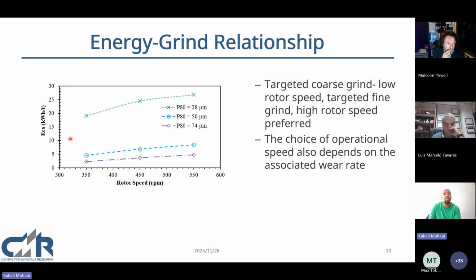As you can see, the specific energy consumption increases with increasing rotor speed, but the curve shows a decreasing trend, so the gradient decreases as the rotor speed increases. However, as much as this data could show that operating at high speeds in stirred milling would be beneficial, there's also a potential impact of grinding media wear and equipment wear, which were outside the scope of this research. Hence, although it's possible to go very high in rotor speed in stirred milling devices, sometimes it's not necessary, as it could lead to other costs, including wear rate and machine wear.